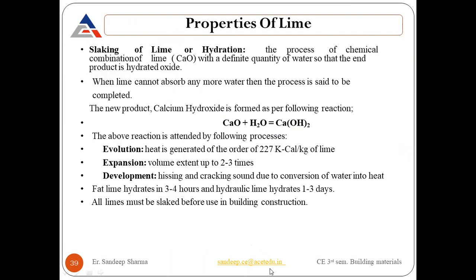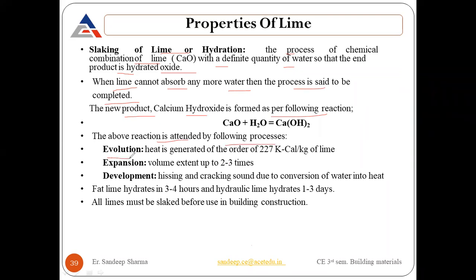One of the most important properties is slaking — the hydration process, which is the chemical combination of lime with a definite quantity of water so that the end product is hydrated oxide. When lime cannot absorb any more water, the process is said to be completed. The new product calcium hydroxide is formed. The reaction is attended by: evolution of heat of the order of 227 K-Cal per kg of lime, expansion of volume up to two to three times, and development of hissing and cracking sound due to conversion of water into heat.